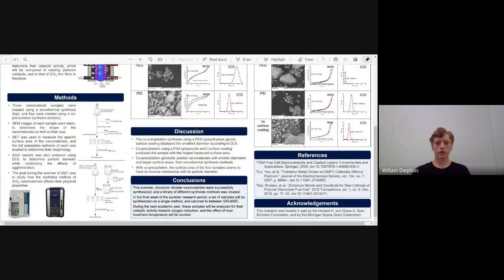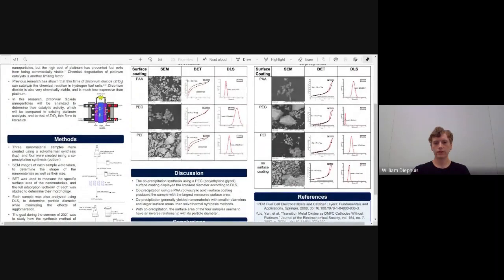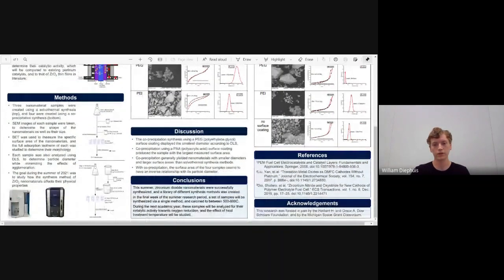Conclusions for the synthesis phase of our research this past summer are that the 2 most reliable synthesis methods that produce the best results for us are coprecipitation using PAA, or polyacrylic acid, in the top row, and coprecipitation with no surface coating shown in the bottom, because these have 2 of the highest surface areas, which is one of the most important properties for catalyst materials.